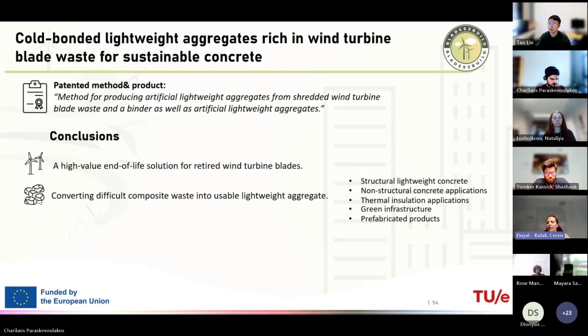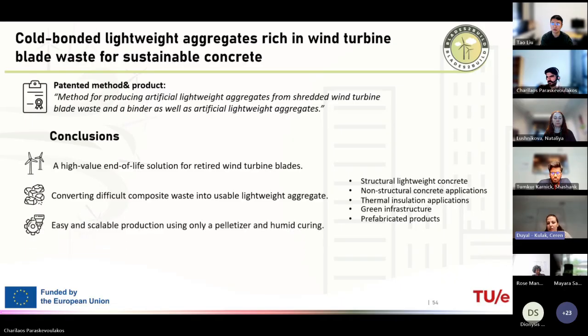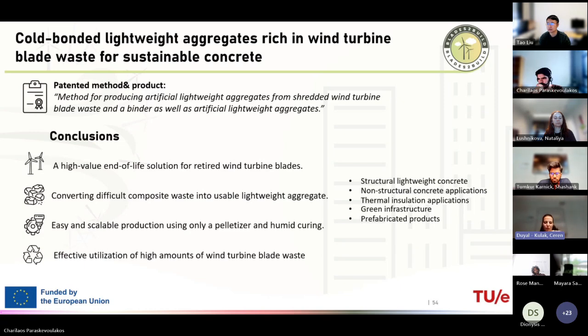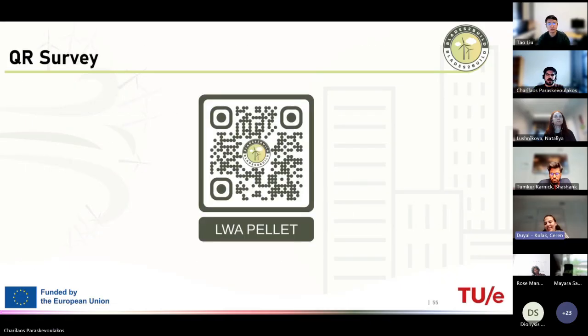So it could be structural lightweight concrete, playing around with the pelletization process to increase its strength. It can be used in non-structural applications, in thermal insulation applications, for green infrastructure, or sometimes for lightweight filling materials, prefabricated products, or it also has a benefit for transportation of the waste, which has a lot of dust. And because it has very low energy consumption, as it's just cold bonded pelletization, it is easily scalable, and just humid curing, there is no heat or other curing methods. It also allows us to use a high amount of wind blade waste in the aggregates themselves, or in the product that the aggregate is put in, like concrete or mortar. Yeah, thank you. This is all from my side.